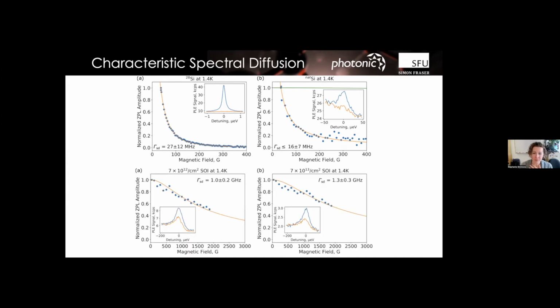And so this top here is, we have a characteristic spectral diffusion of less than 30 megahertz. It's actually on the order of like 10 megahertz, and in measurements that we've done since. And that's true for the silicon-28 or the natural silicon. So these bulk crystals are on the order of like 10 megahertz or something in terms of total characteristic spectral diffusion, like long time, total wandering kind of spectral diffusion, not the instantaneous one, right? This is like the total wandering of any given defect.